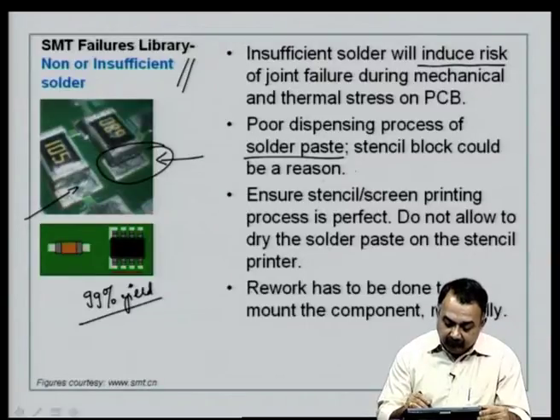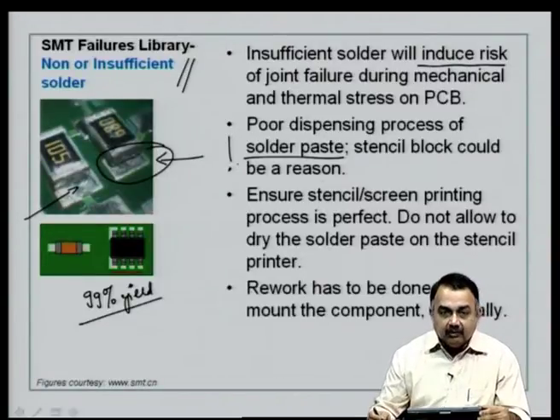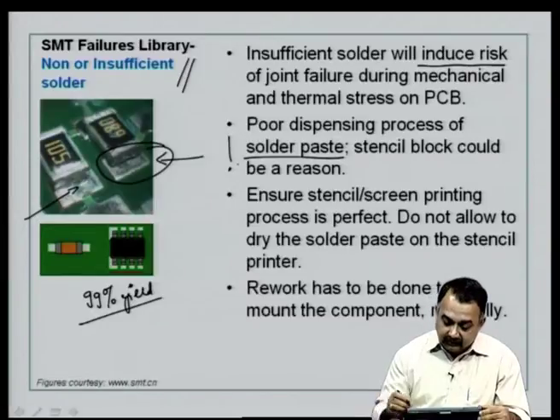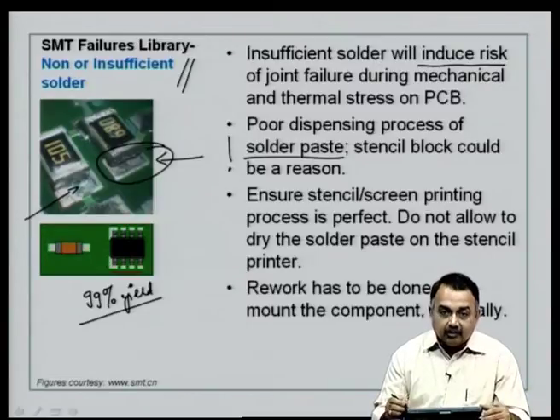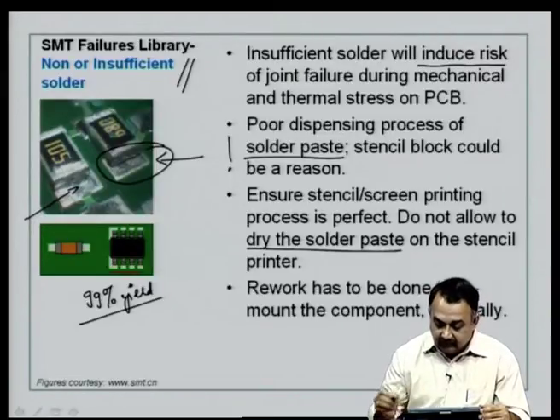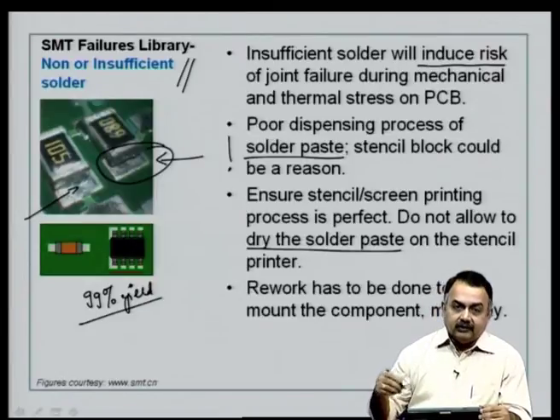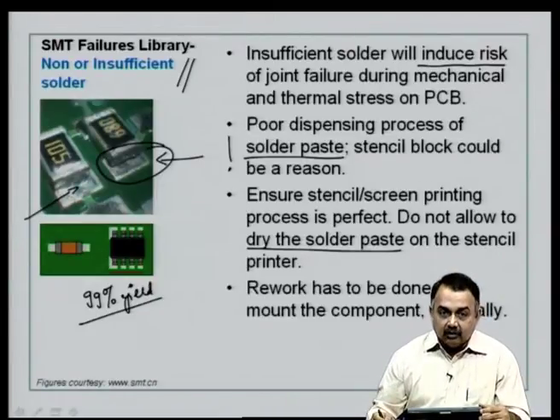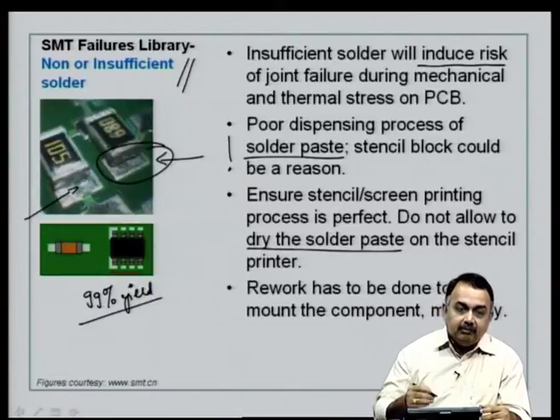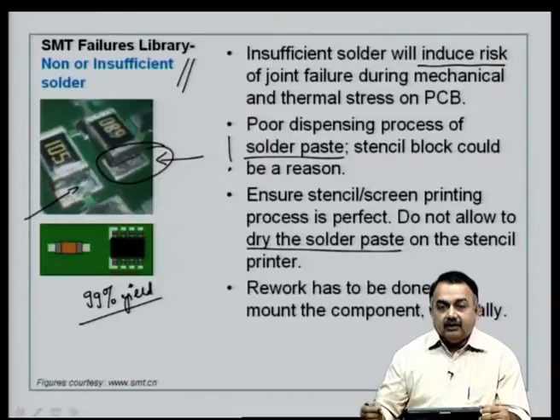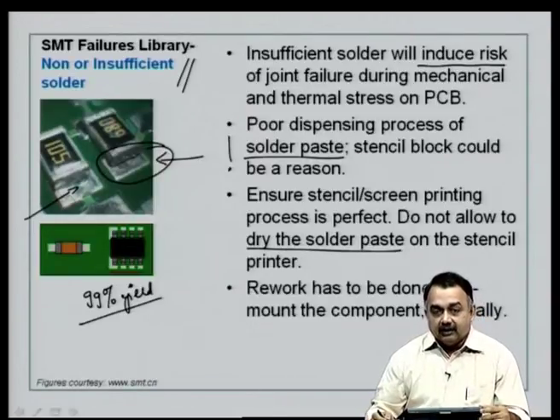Therefore, stencil block could be one major reason that you should think about when you look at this kind of failure. So, in such cases, you ensure that the stencil or screen printing process is perfect. How do you do that? You clean the stencil with the appropriate cleaning material, and then do not allow the solder paste to dry on the stencil printer. So, the technician by experience would not do that. Once the process is over, and if there is a gap between this printing batch and the next, obviously you have to keep the stencil and the work table of the stencil printer fairly clean, so that the material does not dry.